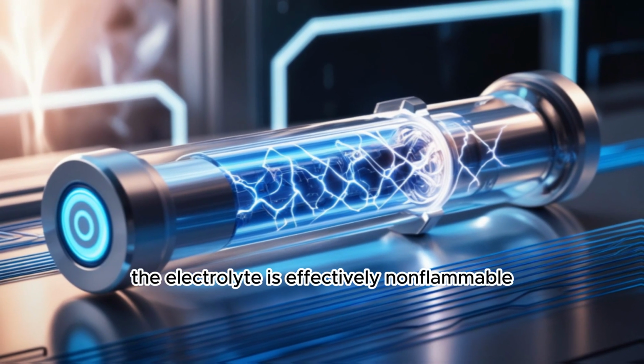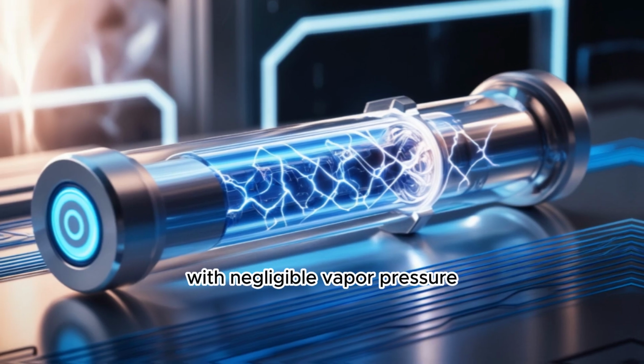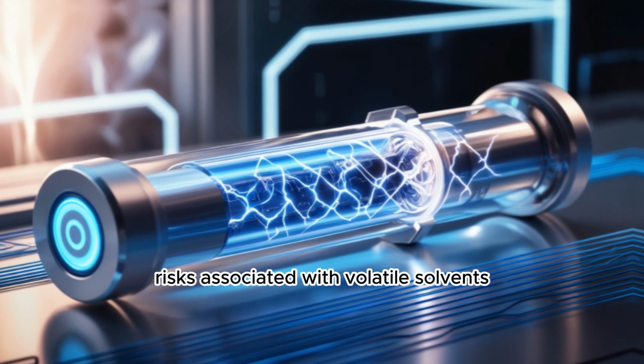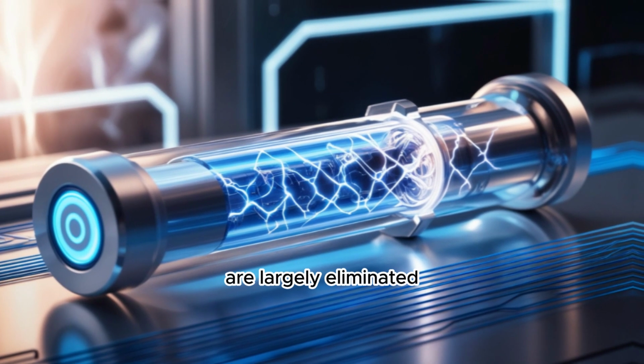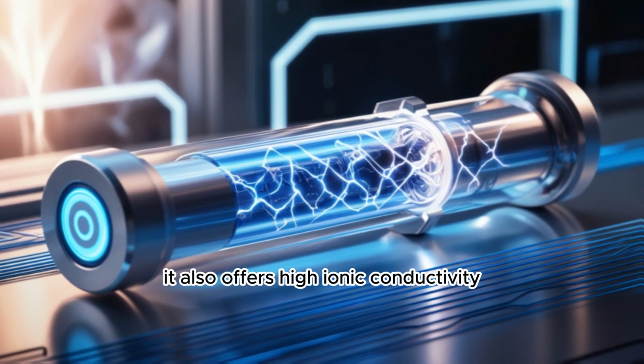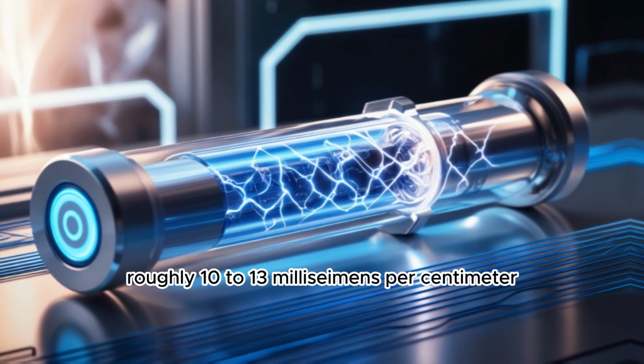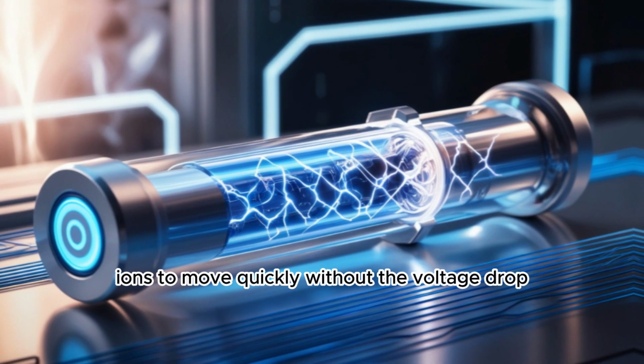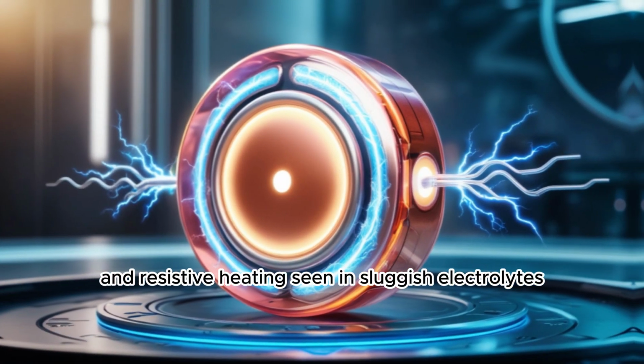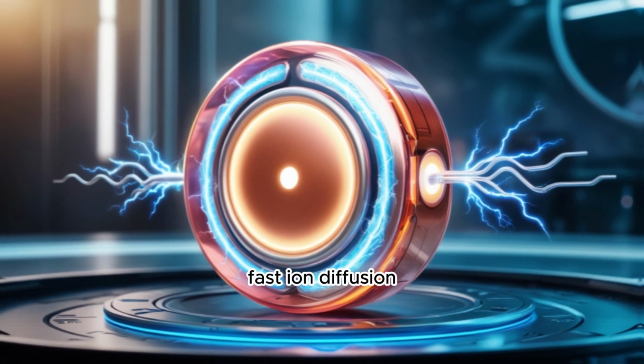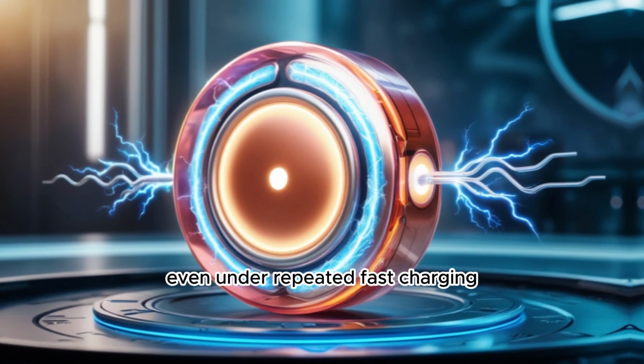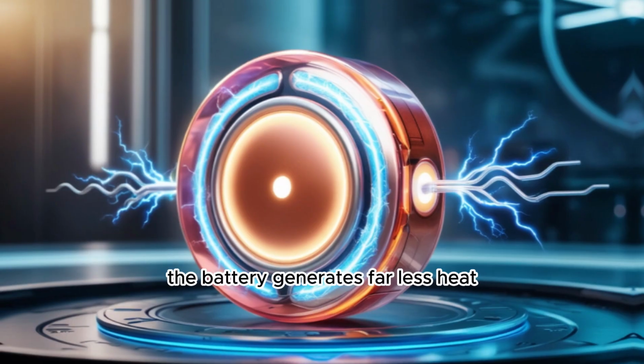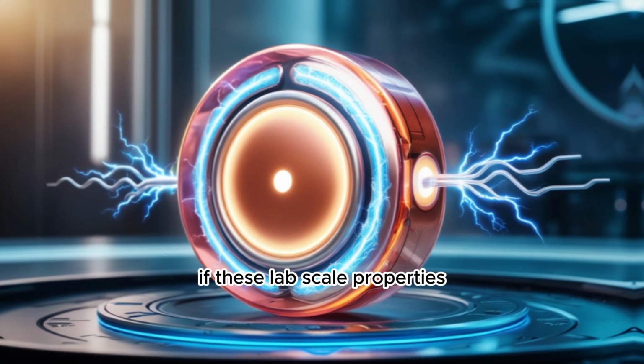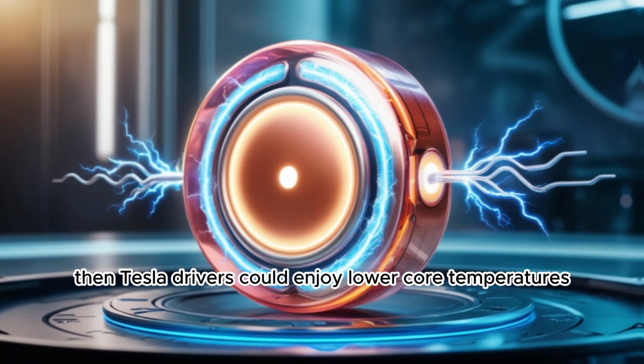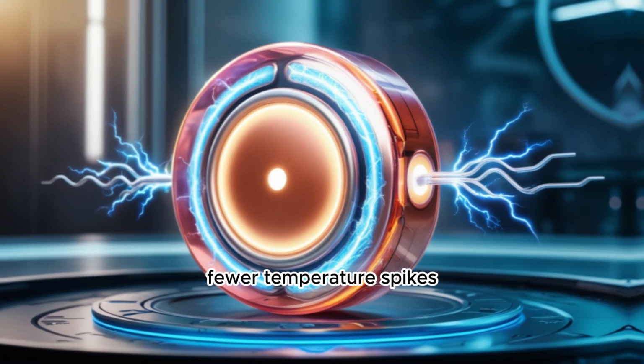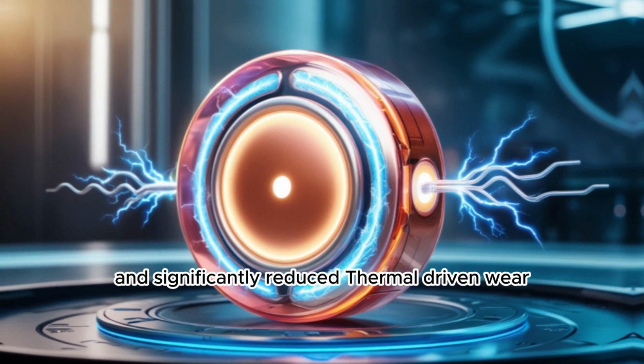The electrolyte is effectively non-flammable, with negligible vapor pressure, meaning the catastrophic fire risks associated with volatile solvents are largely eliminated. It also offers high ionic conductivity, roughly 10 to 13 millisiemens per centimeter at room temperature, which allows ions to move quickly without the voltage drop and resistive heating seen in sluggish electrolytes. Fast ion diffusion and stable aluminum plating kinetics mean that even under repeated fast charging, the battery generates far less heat. If these lab-scale properties translate into mass-produced packs, then Tesla drivers could enjoy lower core temperatures, fewer temperature spikes, and significantly reduced thermal-driven wear.